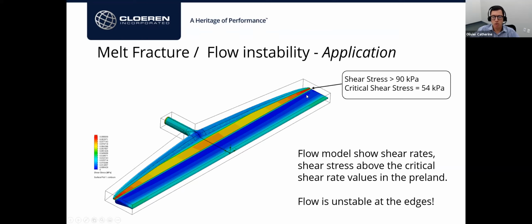And so I think what's going on is that we are starting to see some flow instability in the die flow channel, and this flow instability will not dampen, or will actually continue to be unstable as the material is flowing out of the die. And that's exactly what they saw at the edges of the sheet there.